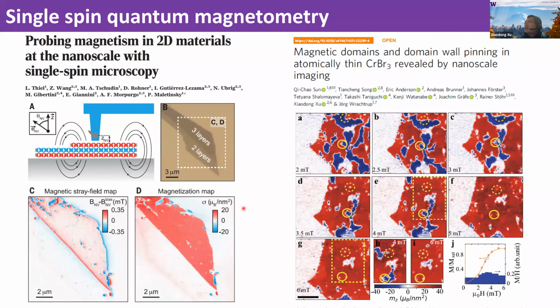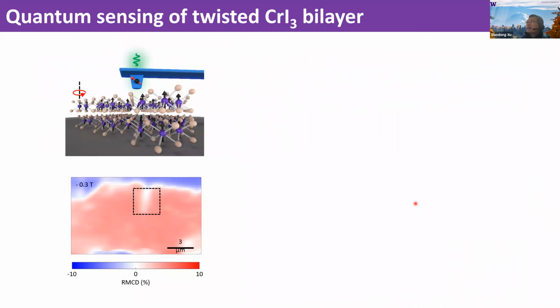Another work we collaborated on with Jörg Wrachtrup's group at the University of Stuttgart. We also measured the magnetic domain effects in atomically thin chromium tribromide. So this is also a bilayer. In this work, I'm not going into detail. Basically, we measured the domain evolution as a function of magnetic field. What we found is that the domain is actually pinned by local defects. So now, with the availability of this technique, we apply it to measure the domain patterns in twisted bilayers. Okay, so again, I show you the MCD maps, and we focus on this little square here.